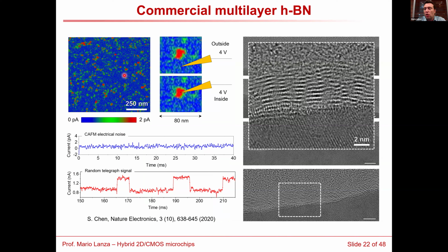And this picture looks very, very similar to the typical picture you observe if you measure a metal oxide used in memristors, like hafnium oxide. So when we saw this, the first thing that we thought is this material is a candidate for exhibiting resistive switching. We also made, with the conductive AFM, another electrical test, which basically consists of applying a constant voltage